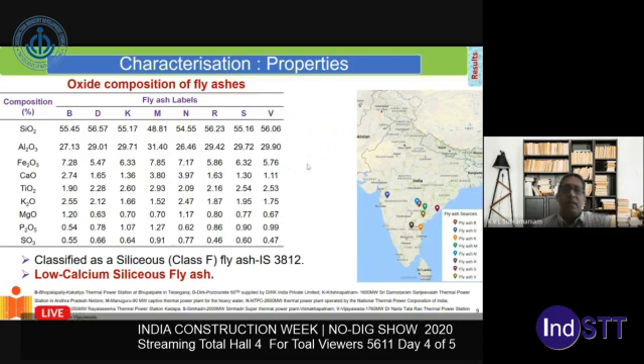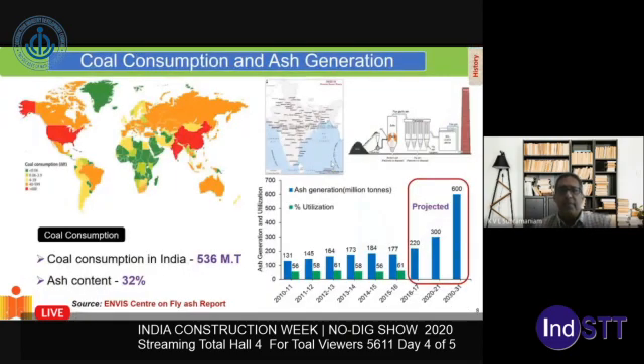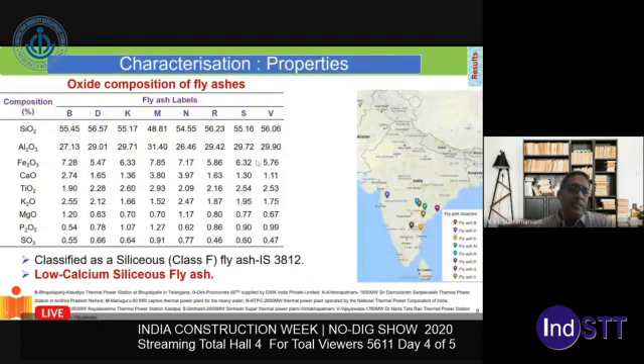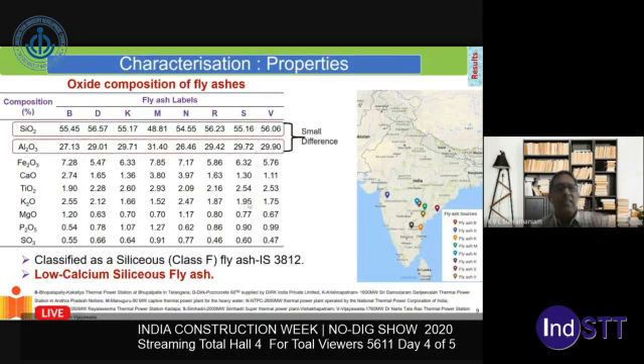So if you now look at the fly ash in India, if I just go to the previous slide, this map of India here shows the different thermal power plants in India, and there is an almost equal geographic spread of these coal burning power plants across India. But what we did initially, to come up with solutions, is we first wanted to understand this fly ash. So fly ash was collected from different power plants across the country, and it was analyzed. And what we found is that most of the fly ash, if you look at just the oxide compositions, has a very small difference in the oxide compositions. But when we started using this fly ash in concrete, we found that the results were night and day. There was a big difference in the final strengths, the final properties that were achieved with these fly ashes.